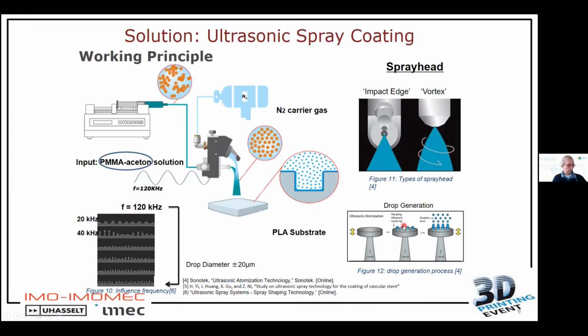These standing waves, if you add more and more energy to them, become higher in amplitude and also thinner at the top. Due to this thinning effect, you create droplets that spread off. And that's the interesting part of ultrasonic spray coating, because these droplets just pinch off of the generated waveform, they do not have much kinetic energy. So you need a carrier gas. We use nitrogen as a carrier gas to bring these droplets towards the substrate.